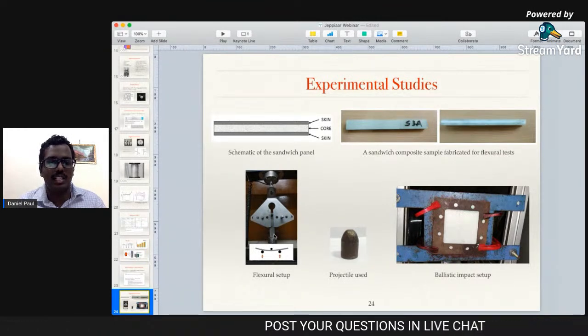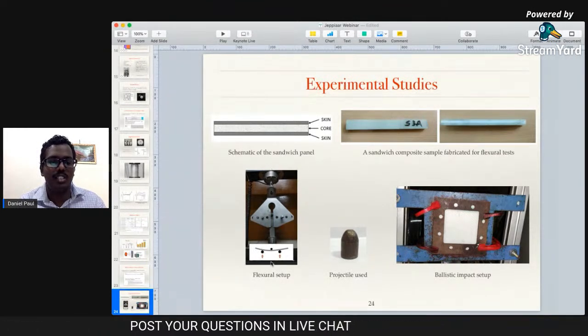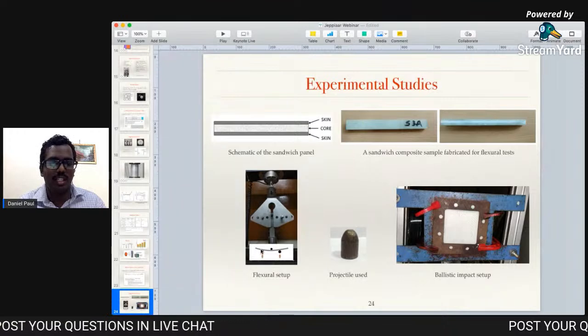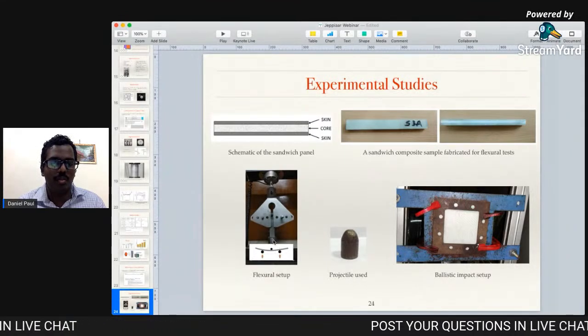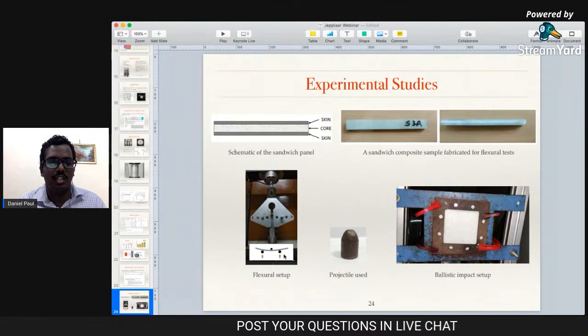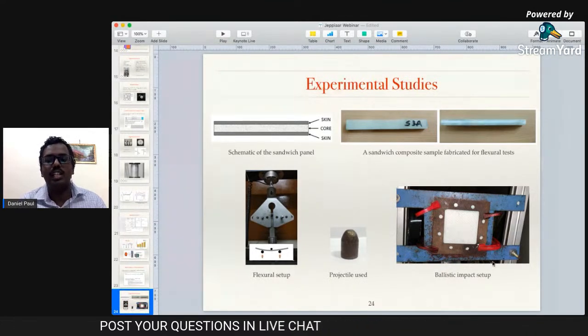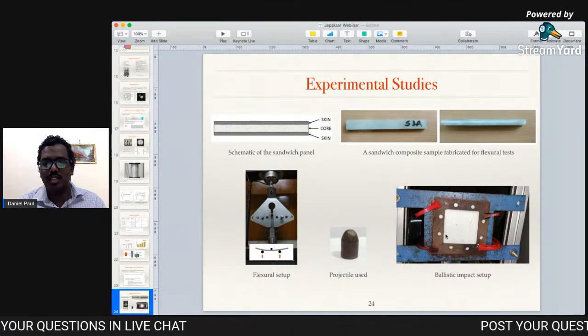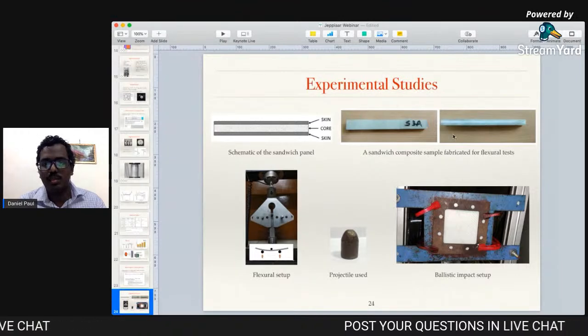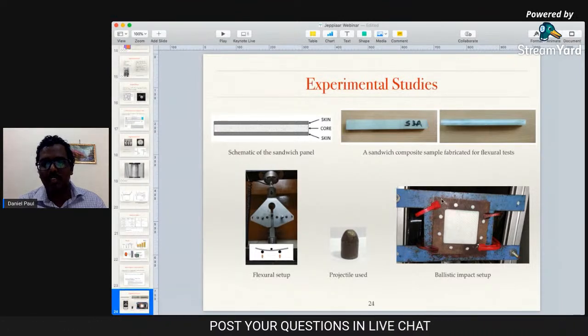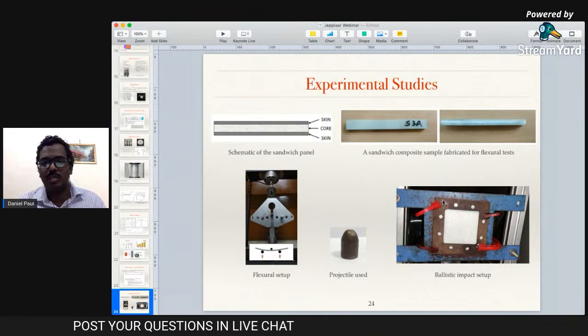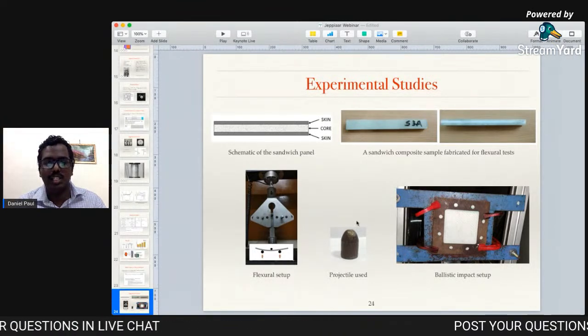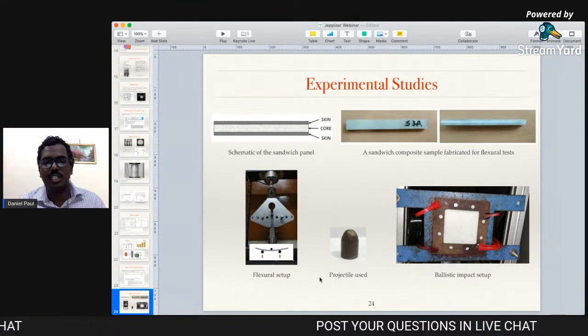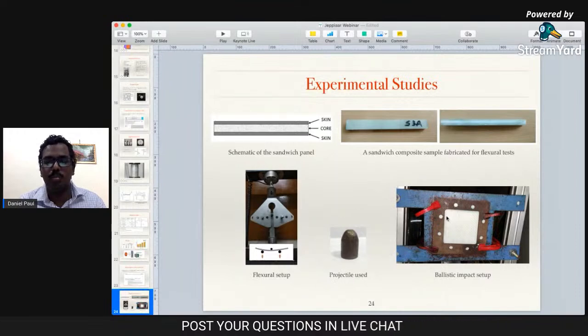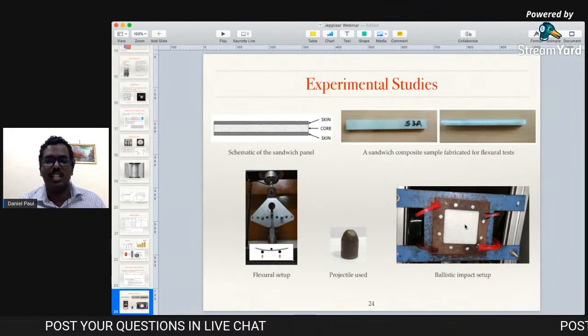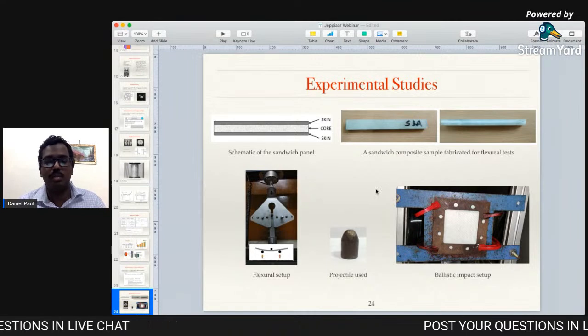And this is the setup that we use, the flexural setup, which is a 3-point bending setup in which there are 2 supporting pins and 1 pin which applies the load and causes the bending. And this is the ballistic impact setup which we had used, in which we can see a similar sandwich plate, which is held in place to a rectangular frame using C clamps. And this in the middle is the metal projectile that we used to impact these sandwich plates and to find out how they behaved.